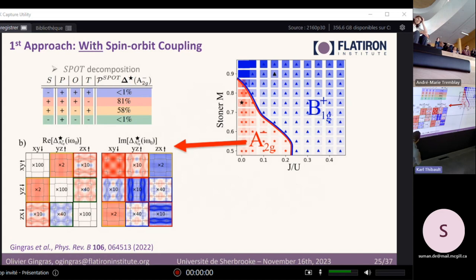And so in this paper, we argued that this state, because it's odd frequency, is vanishing at the Fermi level. So it doesn't really open new gaps at the Fermi level. It doesn't change really at the Fermi level. And this other part here that is odd in orbital mainly couples different orbitals, which happens at different energies than the Fermi level. So we argued that this A2G state here, being odd frequency, would not contribute a lot to the specific heat.